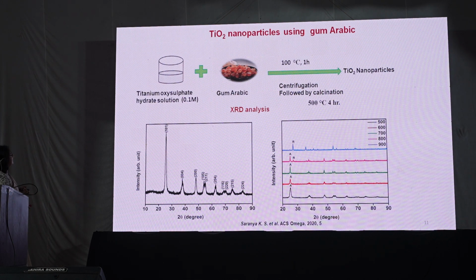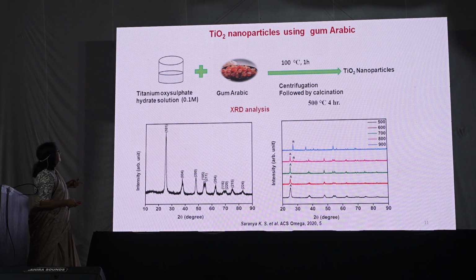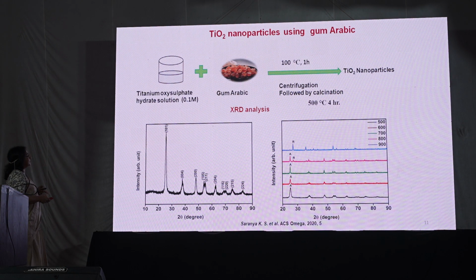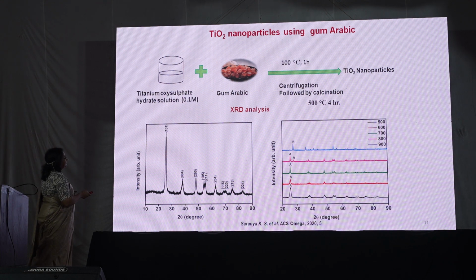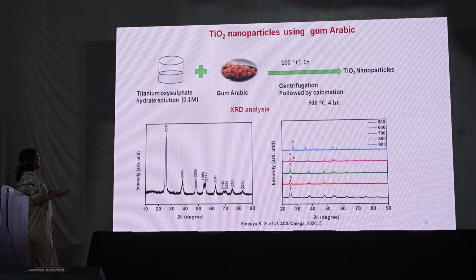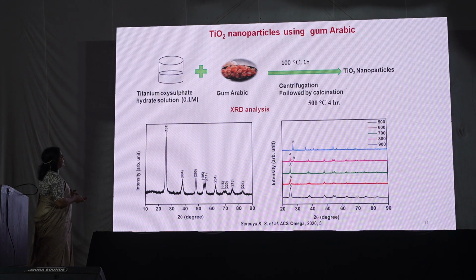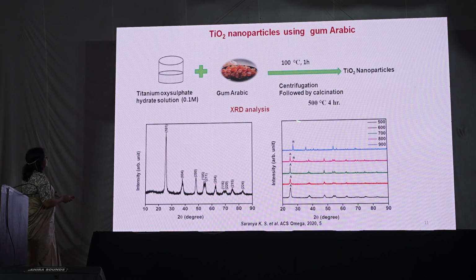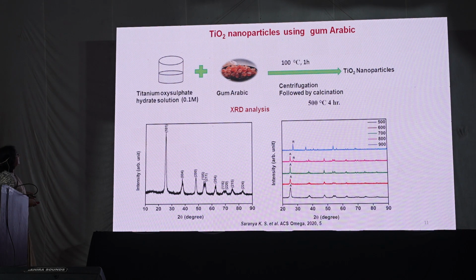In the first study, we synthesized titanium oxide nanoparticles by using titanium oxysulfate hydrate solution and gum arabic as a precursor molecule that will act as the reducing and stabilizing agent due to the presence of hydroxyl, carbonyl and carboxyl groups. For this we simply mix this at 100 degrees Celsius for 1 hour, and after centrifugation followed by calcination at different temperatures, we can synthesize the titanium oxide nanoparticles. We synthesized at 500 degrees Celsius for 4 hours, and we got the nanoparticles here, and these are characterized by XRD.